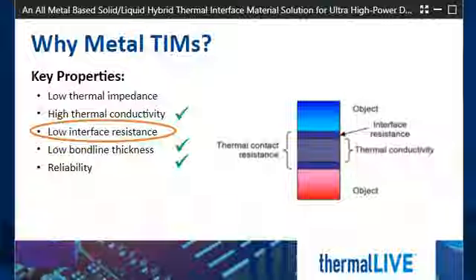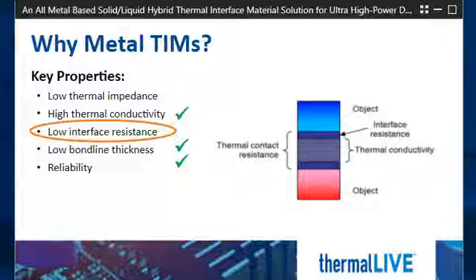For instance, copper has 386 watts per meter Kelvin thermal conductivity, but it can't be used as a thermal interface material because it's a very rigid metal. With power cycling, compared to some typical phase change material and thermal grease, thermal resistance for those two materials will grow over time, and with compressible TIM, it will drop down at the start, and after that it will be pretty stable.